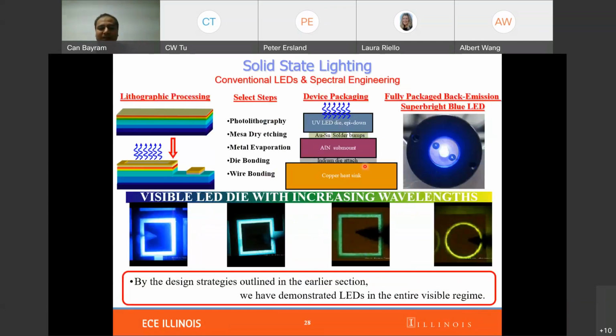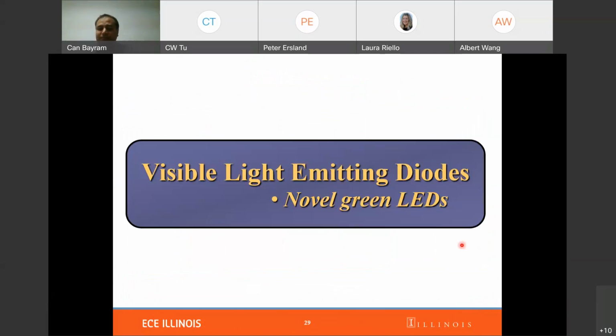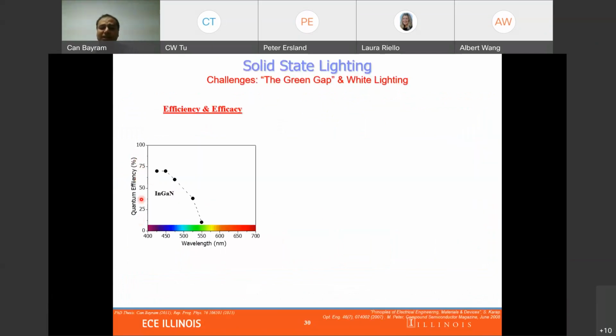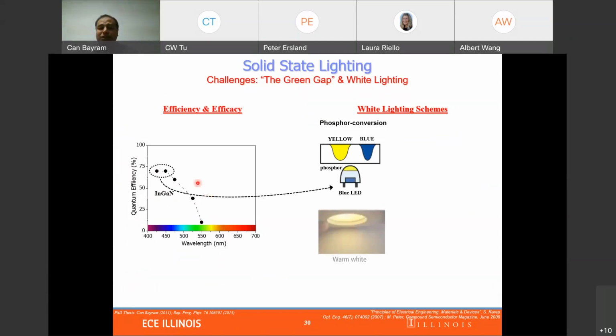So my group works on these different types of LEDs, and we fabricate a variety of structures using our facilities from blue to green. What I'd like to focus on is the need for a green LED. So when we look at the efficiency of these LEDs as a function of wavelength, we notice that with going from blue to green, we put more indium and your efficiency goes down significantly. So typically, the white lighting schemes involve a blue LED that comes from indium gallium nitride material system with a phosphor, so that you can create the yellow light and you receive what we call a warm white structure.